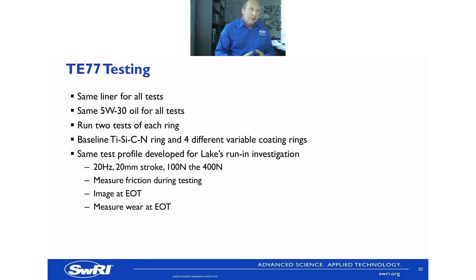So let's start the beginning of this with the TE77 testing. As I said, it's the same liner for all the tests. We used the 5W30 oil, the same one for all the tests. We ran 2 tests with each ring just to make sure we weren't seeing any outliers. The baseline TiSiCN ring that we developed previously, we coated and used as our baseline. And then we tried 4 different variable coating rings. We did 6, but 2 were clearly not working, so we only had 4 that we could try. Same test sample profile developed for Lake's run-in investigation.